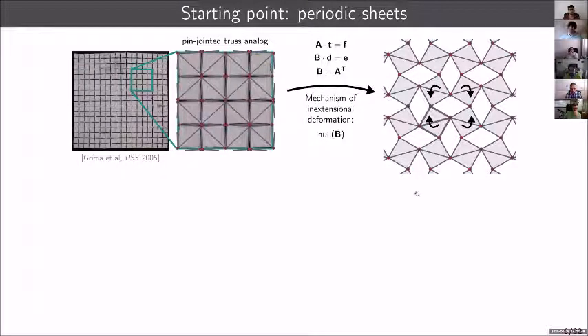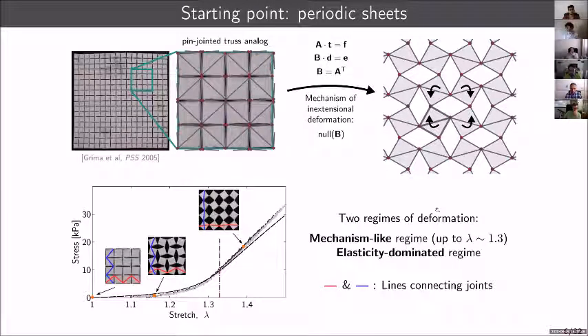There is no mechanics. But now, if you want to look at the mechanics, what we did was to perform experiments and numerical simulations on this sheet, and we plotted stress versus stretch. You can see that there are two regimes of deformation. There is a first regime that you see over here, that is a low stiffness regime. And then there is a second one after more or less 1.3 stretch that is much stiffer than the other. Just to give an idea, the continuous curves are experiments and the dashed one is a numerical simulation. Since the sheet is isotropic, the response is identical along both directions.